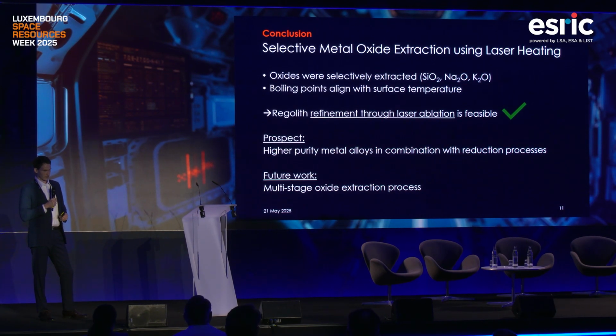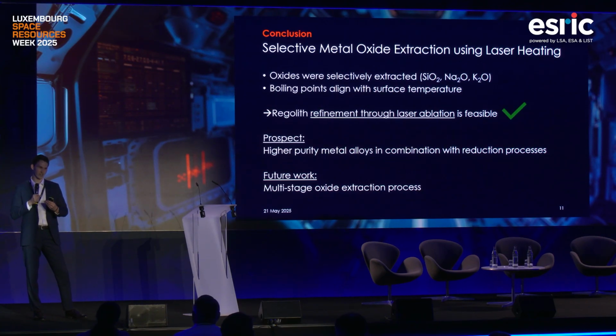That already concludes my talk. We were able to extract oxides, which we believe to be, though we have not yet performed XRD to find out, silicon dioxide, sodium oxide, and potassium oxide. It seems that the boiling points of these oxides align very well with the surface temperature that we got. So we believe that we can refine regolith based on these boiling points of these oxides to a certain extent. That means that refining regolith through laser ablation is feasible, and that is something we should look into further, with the prospect that we can combine certain methods in order to produce higher purity metal alloys.